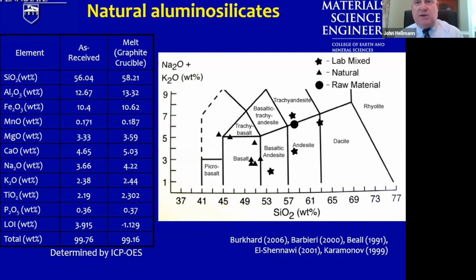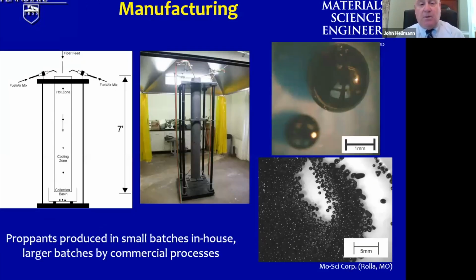The issue is that during that crushing and grinding process, we generate something on the order of 40 to 50 weight percent fines that are too small for use in the roofing product. Therefore, these are put back to landfill at very substantial cost, something on the order of $9 per ton transportation costs back to landfill. So these materials should be available relatively inexpensively and in massive quantities, millions of tons per year. So we procured some of those materials.